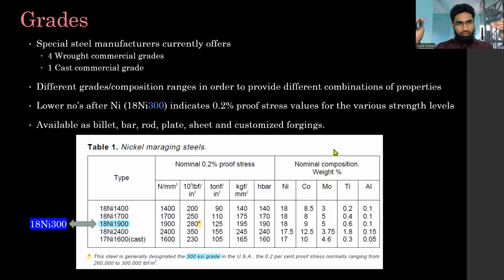So from that material, what they said was that the special steel manufacturers offer the steel in two modes, wrought mode and cast mode, four wrought commercial grades and one cast grade. And this is generally supplied in the annealed and solution treated condition, because it is very tough in that particular state. It is soft as well. Hardness is about 30 to 35 HRC. So it is soft and tough, and correspondingly readily machined and formed. So this is the general state that suppliers supply the material in. If you can see, there are different grades here.